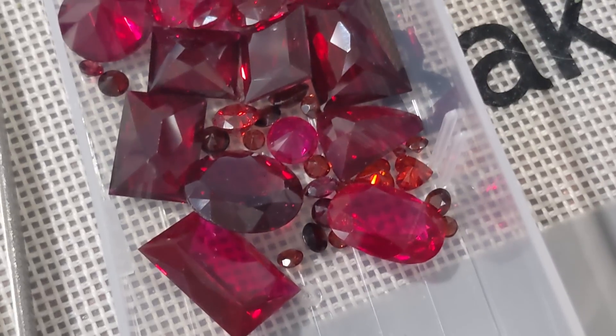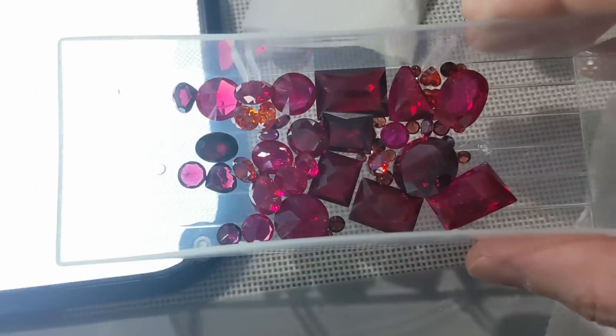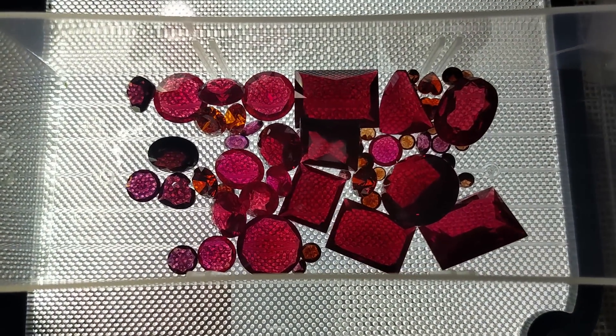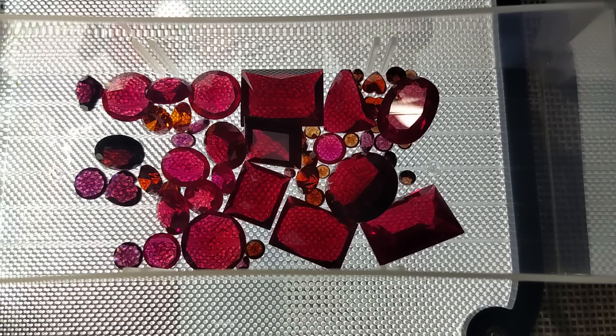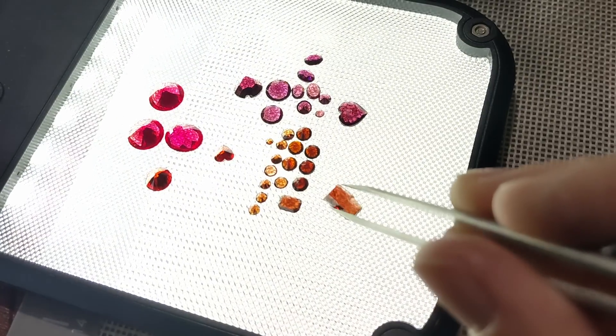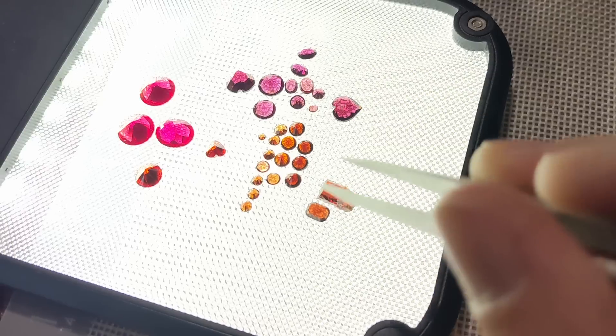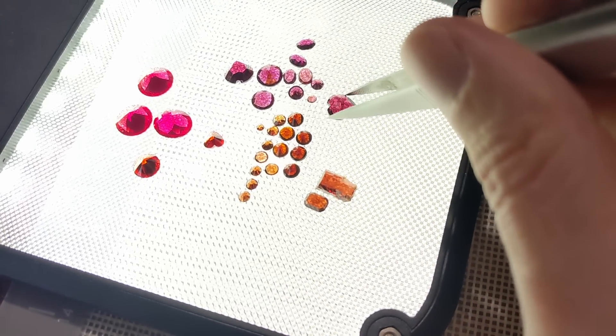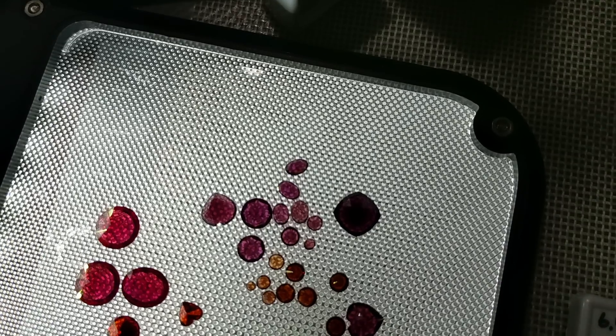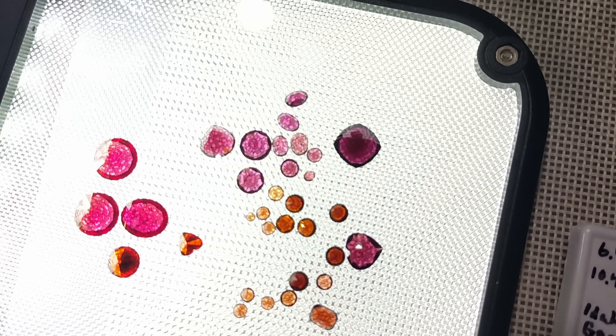There were a lot of reds, and I'll be honest and say I still haven't checked every single one, but just like with the other colors the backlight did a really good job separating out the different species. A lot of them were sapphire, but there were two subtle shades of red and purple. Putting a piece of pyrope garnet down looked nice and red and matched the lower right rows of stones. Compare that to the almandine garnet from Idaho, which on the light table is dark but has a distinct purple tone that's different from the red pyrope or the cherry reddish-pink sapphire.